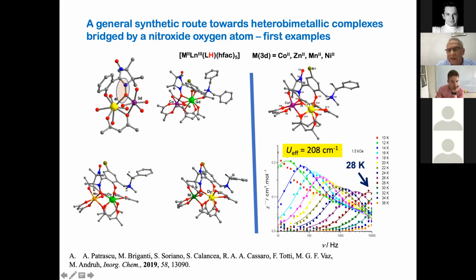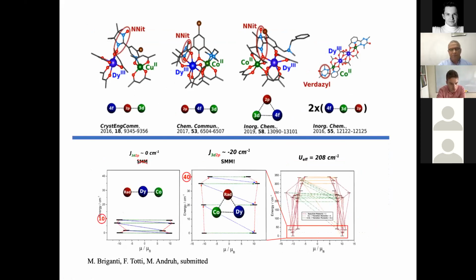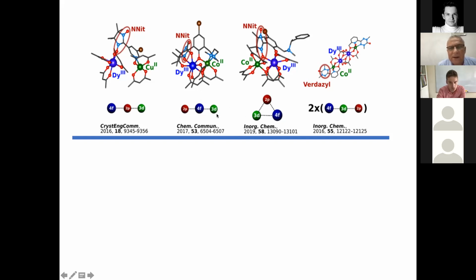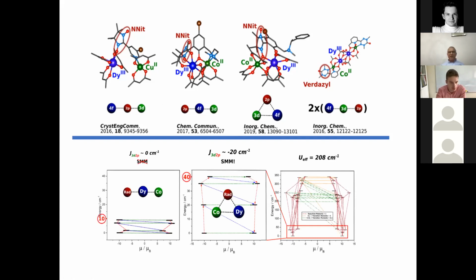And indeed, the 3 spin carriers work together, and this leads to a single molecule magnet with a quite high blocking temperature. All this data have been analyzed by us recently and compared, and this is our first case, and these are other sequences of the spin carriers which have been observed in the literature. And the main result of our work is the fact that the quite strong antiferromagnetic interaction between the 3d ion, in our case cobalt, and the radical will have a strong influence on the energy of the Kramers levels of dysprosium. And this shows for the first time that we can force the 3 spin carriers to work together in order to improve the magnetic properties.